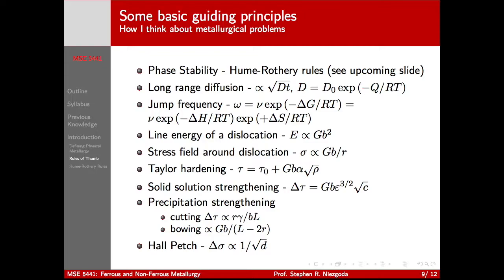What it's going to depend on is the distance between your particles, L, and the radius of your particles, R. It's going to depend on them in different ways. And of course, cutting is also going to depend on the surface energy. Is your particle coherent, semi-coherent, or incoherent? What's the energy of that? If you want to really get into it, it's going to depend on things like the antiphase boundary energy and other stuff, but those are second order effects. Then what happens after the dislocations pass the particles.